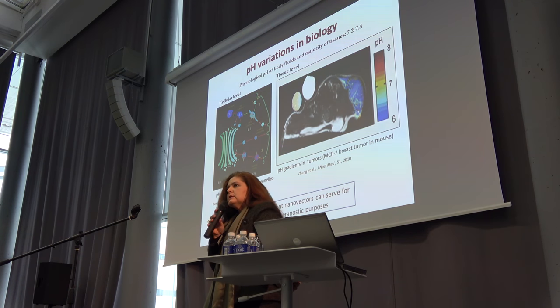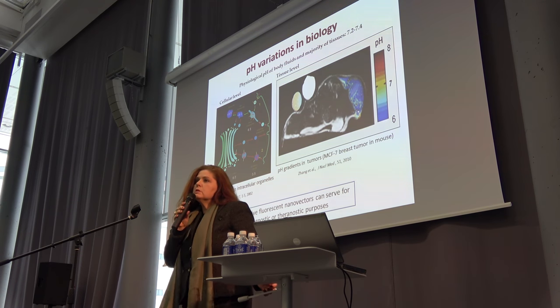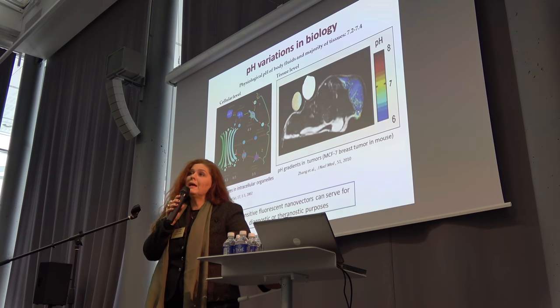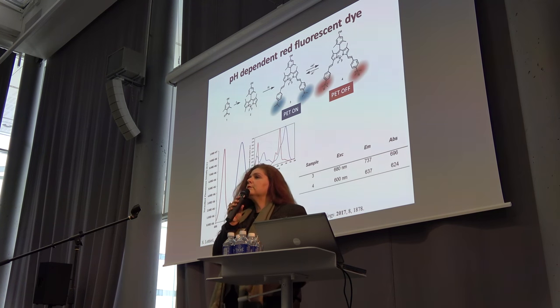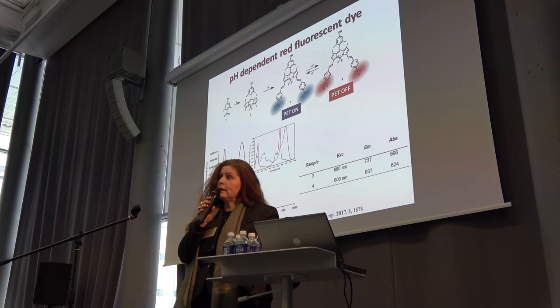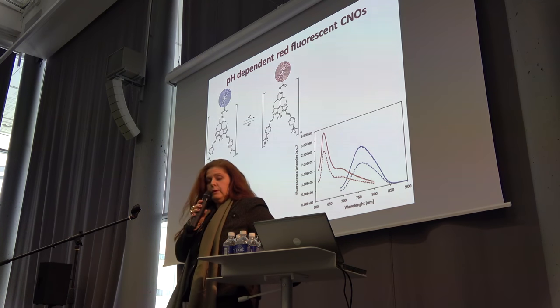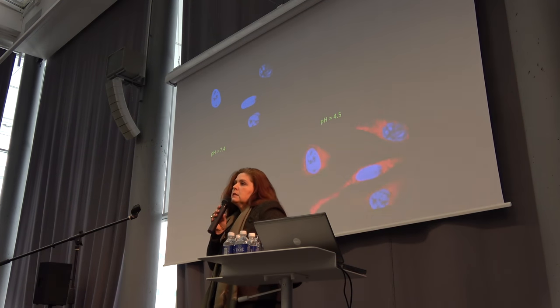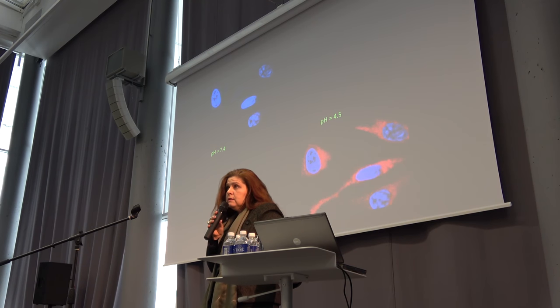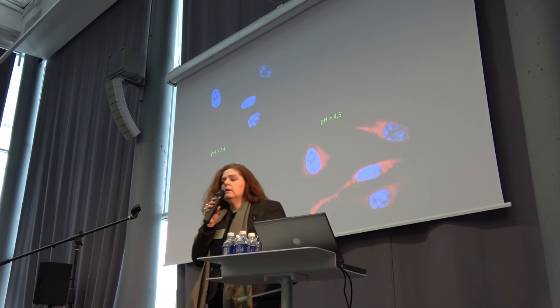As we all know, there are differences in pH at the cellular level, but also in proximity of cancer cells. What we wish to do is design a nano-diagnostic — a nano-vector — that can be used for diagnostic purposes. We have developed a pH-dependent red dye, which we couple on the onion. We can see the red fluorescence only at slightly acidic pH. There is no fluorescence at neutral pH 7.4, but we see nice bright red fluorescence at pH 4.5.